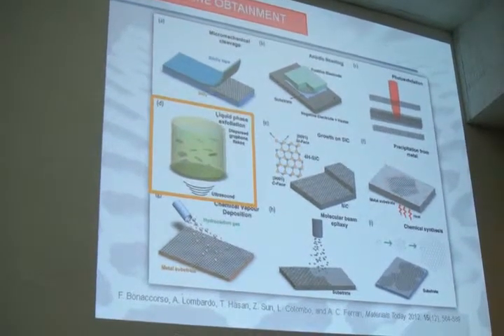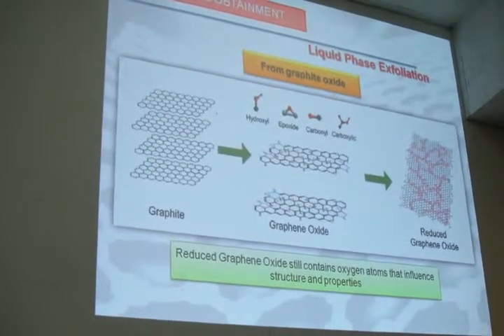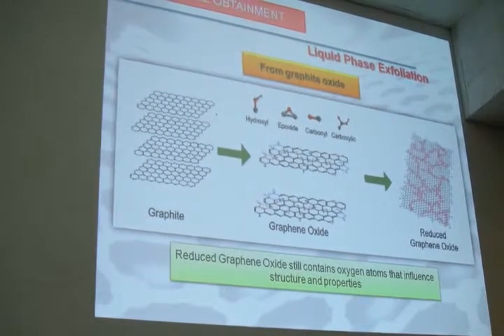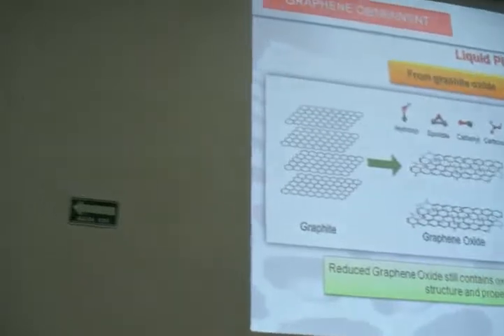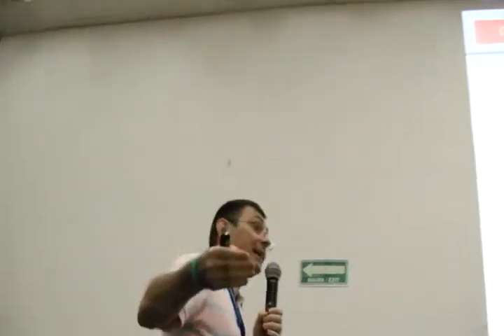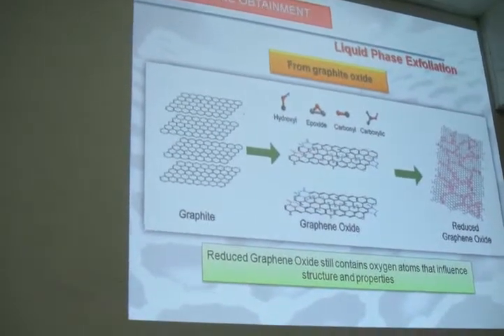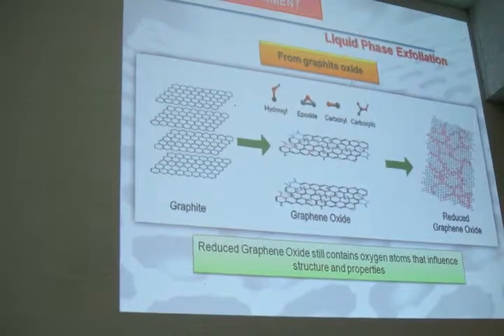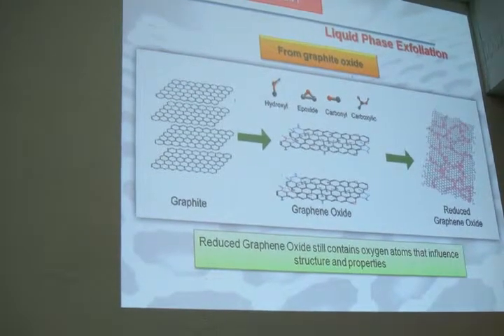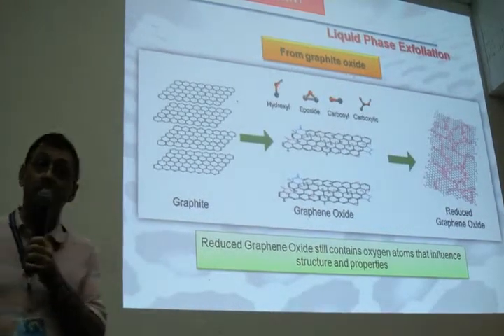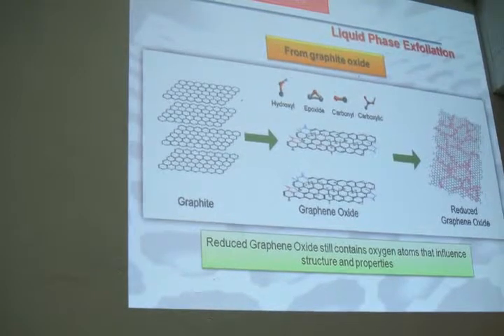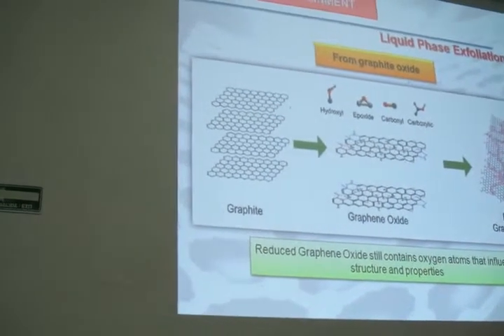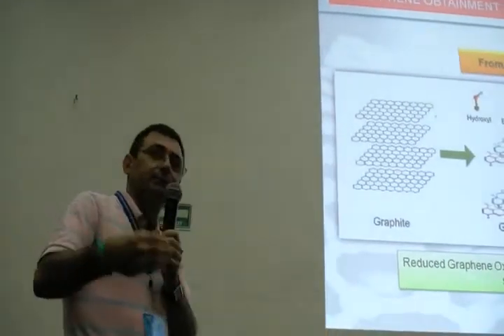This is liquid phase exfoliation. Liquid phase exfoliation is divided in two, actually. In general, most people do the following. They start from graphite, they oxidize graphite. What they get is graphite oxide, which is characterized by the presence of oxygen-containing groups. It means also that carbon atoms are not sp2, but now there are a lot of sp3 hybridized carbon atoms. It means that the conjugation is destroyed. It means that it's a completely different compound. For example, it's characterized by a completely different polarity and a completely different solubility.